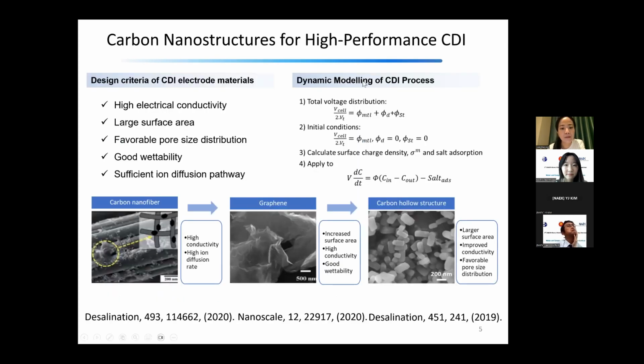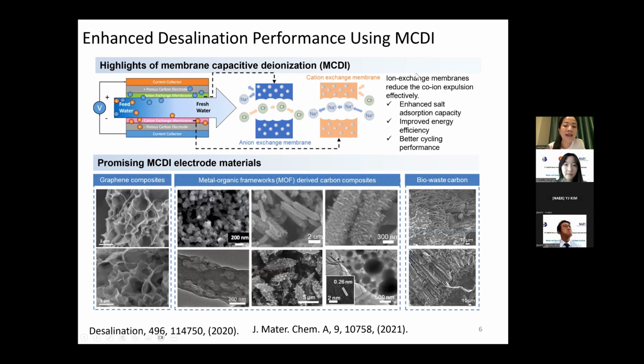So among all these different electrode materials that we can choose to make this desalination electrode, there are some governing rules. We have done some dynamic modeling for the CDI process to figure out a few key parameters that you need to pay attention to when you want to design an electrode. For example, high electrical conductivity, large surface area, favorable pore size distribution, good wettability, sufficient ion diffusion pathways, and so on and so forth. With these few criteria, we can choose the ideal materials for electrode fabrication and also desalination. So with this technology, we can achieve a better version of CDI to remove the sodium and chloride from salty water.